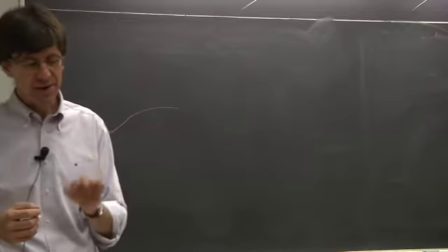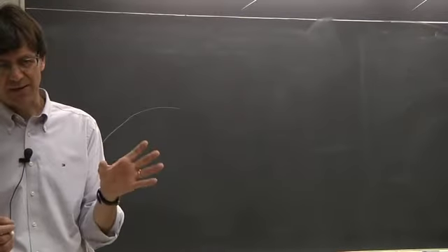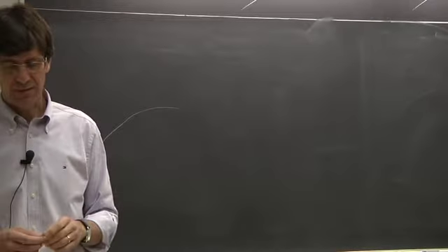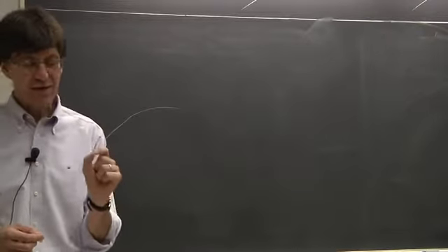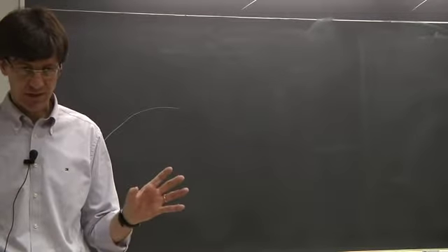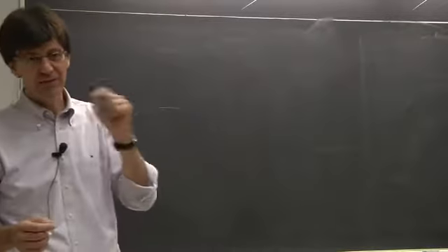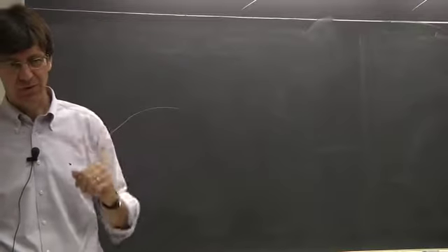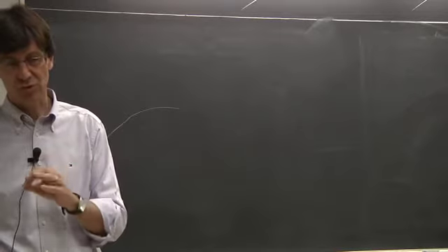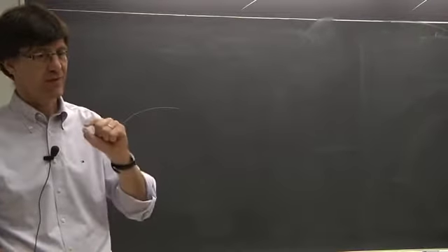Let's say the crucial parameter here is how much is the change in the binding, not really the value of the binding energy, because you can find some source of X-rays for that particular binding energy. The point is really how much the binding energy changes as a function of the local environment, because you need to be able to measure a few electron volts out of 1,000 electron volts of photon energy, right? So your technique must have a very good resolution, of 10 to the minus 3 in this particular case, in order to be able to detect 1 electron volt.